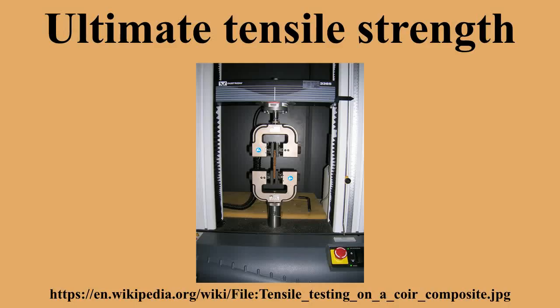Typical tensile strengths. Many of the values depend on manufacturing process and purity. B. Multi-walled carbon nanotubes have the highest tensile strength of any material yet measured, with labs producing them at a tensile strength of 63 gigapascals, still well below the theoretical limit of 300 gigapascals. The first nanotube probes whose tensile strength was published had a strength of 3.6 gigapascals. The density depends on the manufacturing method, and the lowest value is 0.037 or 0.55.